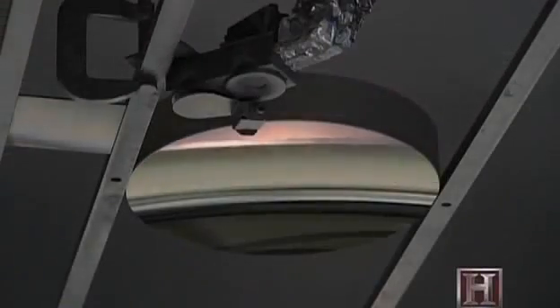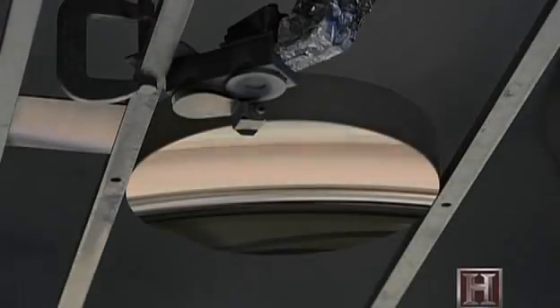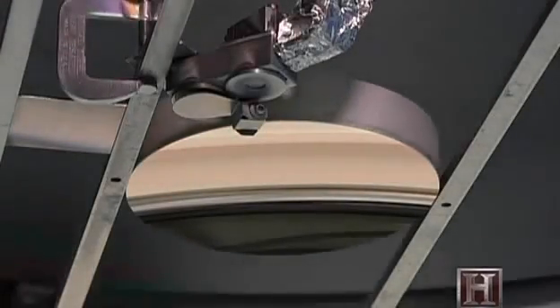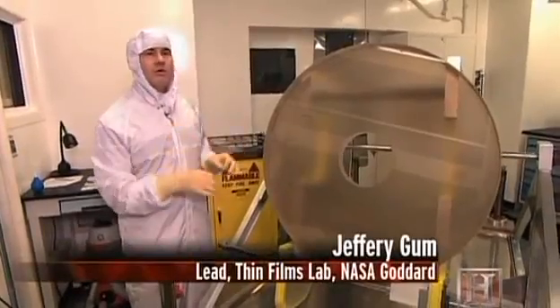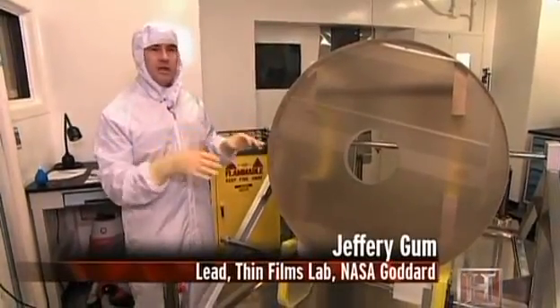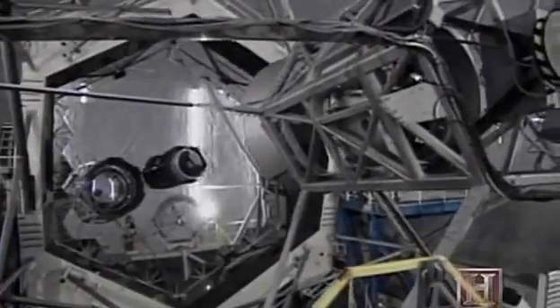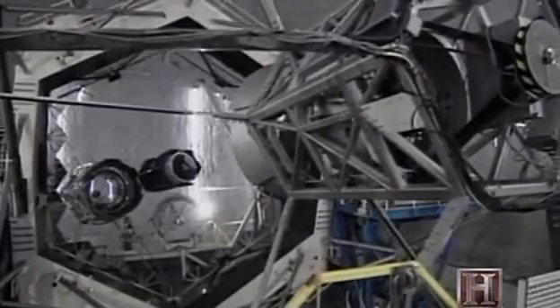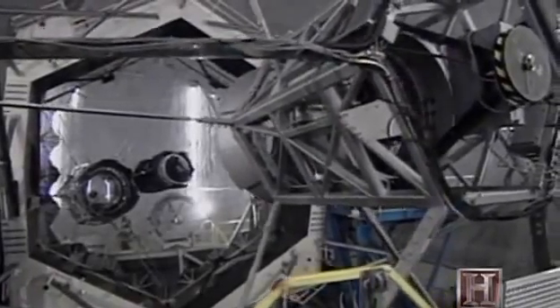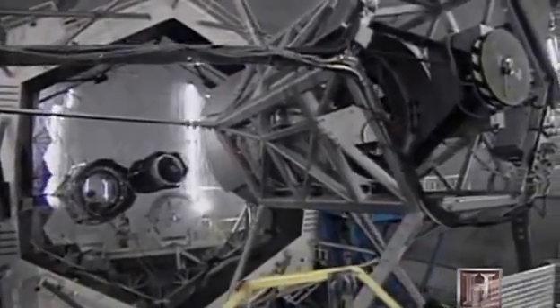But as shiny as the aluminum coating is, it faces a host of enemies. Over time, moisture and pollen and bugs and things like that will get on the optical surfaces, and they'll start etching into the aluminum, and they degrade the coating over time. The only way to restore an aluminum-coated mirror is to remove the corrupted coating and replace it with a fresh one. It's a major event for observatories and a necessity about every 2 years.